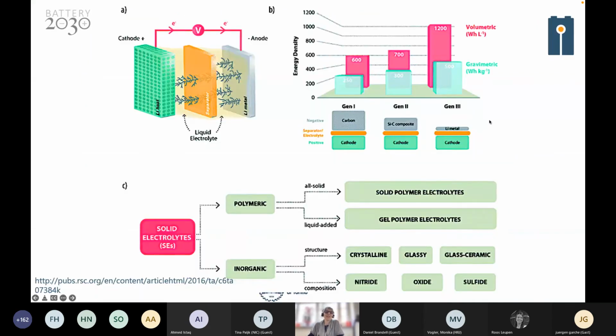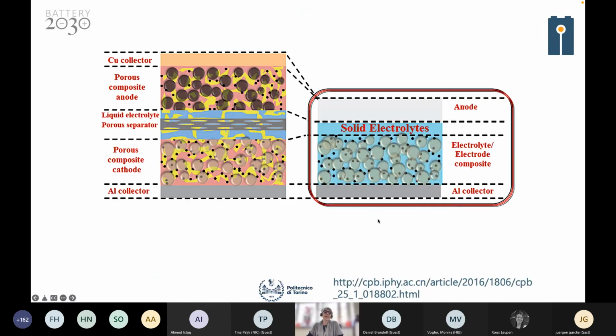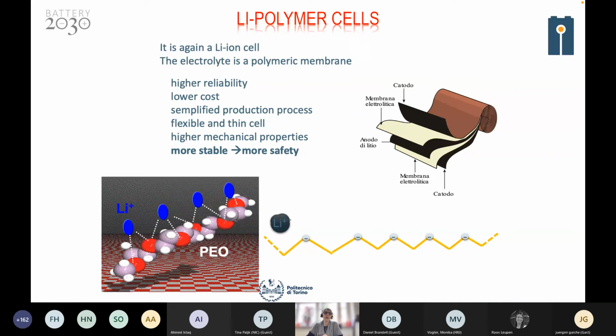Why solid state? When we speak about solid state, we again are speaking about a very wide range of possible configurations: polymer, gel polymer, ceramic, inorganic ceramic electrolyte, but also mixing of all of them. Why? Because when we are eliminating a liquid electrolyte using a solid electrolyte, we can use lithium as anode, so that it will be protected, and this enables the possibility to increase a lot the energy density, but also you have a reduction of the volume of the whole cell. That is very, very important for automotive applications, for example.